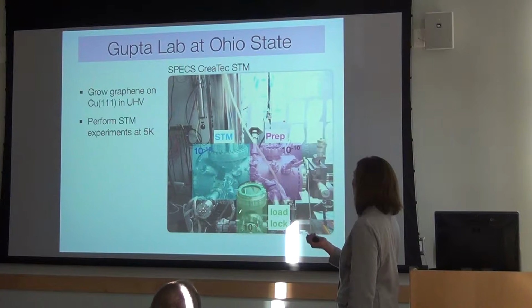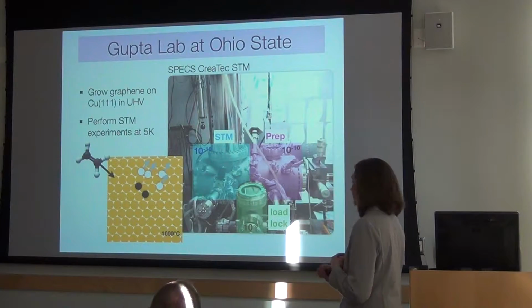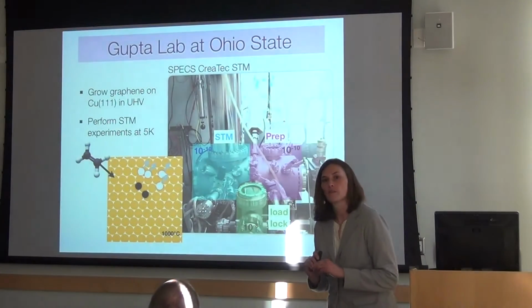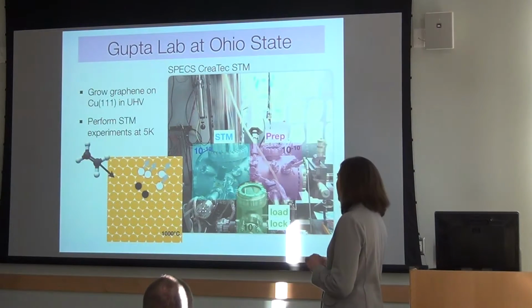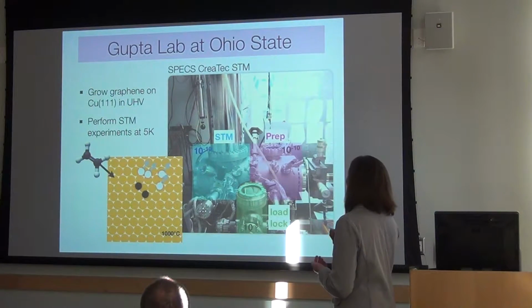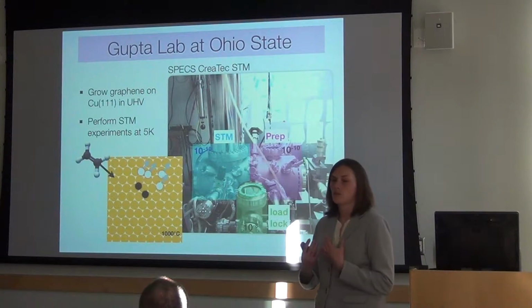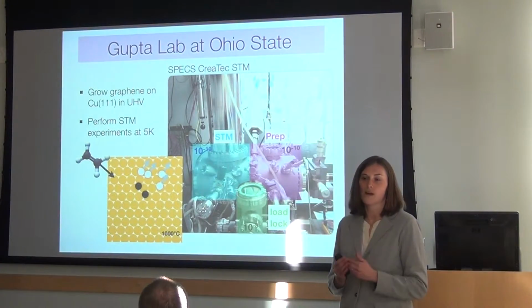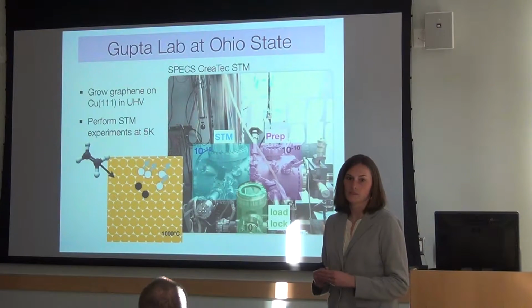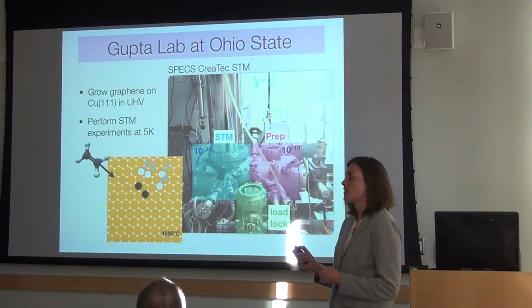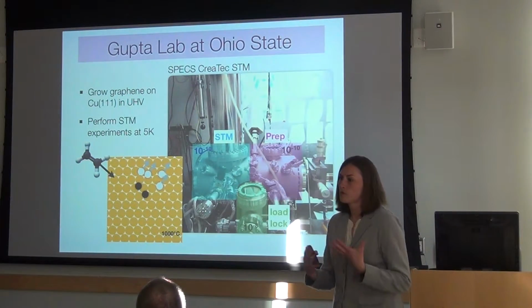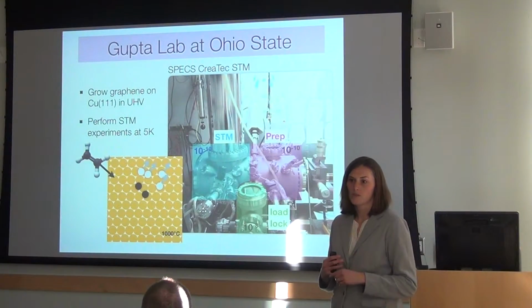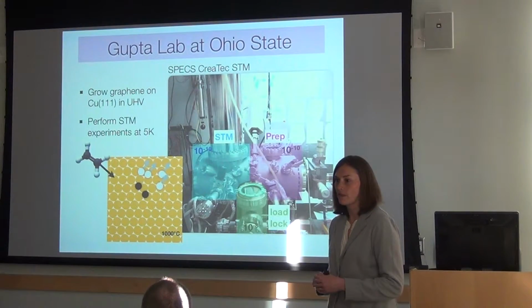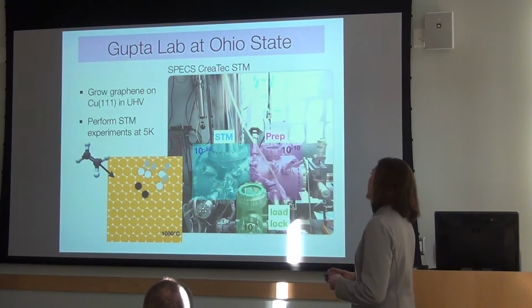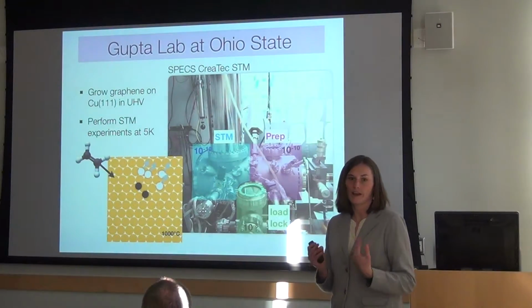Okay. And this is also at ultra-high vacuum. And then very briefly, I'm going to tell you about our growth of graphene on copper. The motivation for doing this in ultra-high vacuum is that you can really well control what's on the surfaces. This is very similar to an atmospheric pressure chemical vapor deposition growth, which is what a lot of people do to grow graphene, except that we had to make some modifications